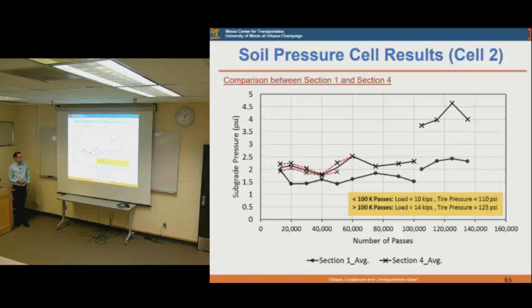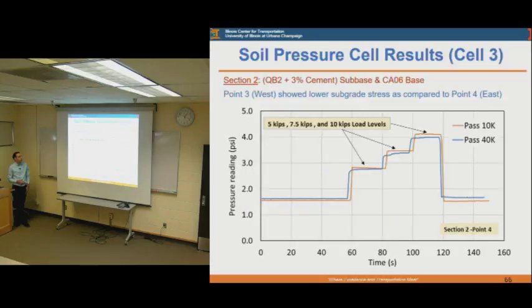When we increase the pressure from 110 psi to 125 psi, and then increase the load from 10 kip to 14 kip, then we also saw some increase in the pressures that are recorded on top of the test sections. In particular, they were higher for section 4, which didn't have the RAP and only had the Quarry byproduct mixed with the cement.